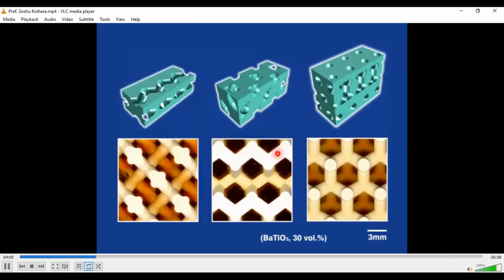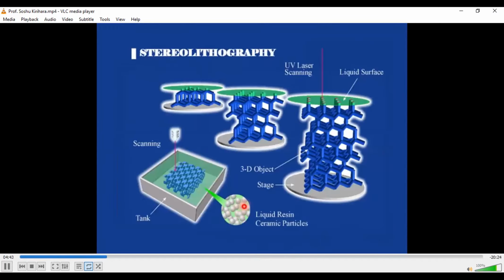This figure shows the created photonic crystals. In this case, an epoxy mold with an inverse diamond lattice structure was created by stereolithography. Barium titanate paste material is inserted into the three-dimensional mold, so we can create a photonic crystal like this. However, it is difficult to inject the material paste into the three-dimensional mold, so we try to mix the ceramic particles into the photosensitive liquid resin.